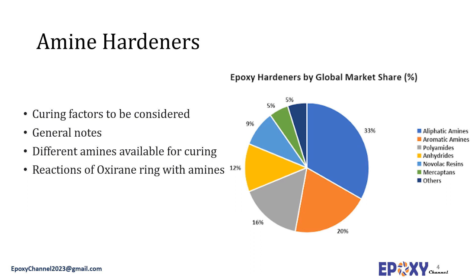To conclude this part, a few notes must be mentioned. First, the choice of amine hardener affects the processing and final properties — epoxies with different hardeners cure differently at different temperatures and rates. The hardener system is chosen based on the structure of the epoxy and the processing requirements. Some epoxies can be cured with a certain range of hardeners; for example, when the resin structure is cycloaliphatic, cycloaliphatic amines are often the best choice. Mixing ratio is another important indicator.